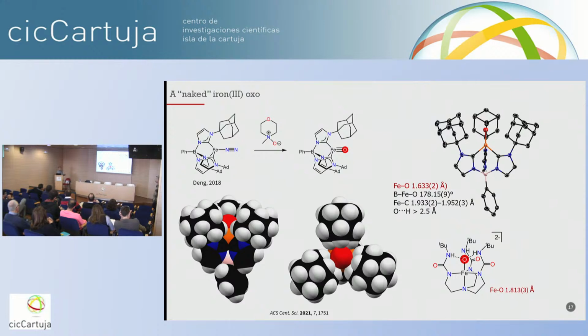Because it reacts with toluene when you heat it up. You synthesize it in THF, and I would be surprised if it doesn't insert the oxygen into the carbon next to the oxygen of the THF. The CH bond in THF is stronger than that in toluene. So it doesn't form a lactone or lactam or anything like that? Not that we can tell. I think this is pretty robust. If you heat this up in benzene, you can heat it to like 100 degrees, no problem for a few hours. You see a lot of papers with iron oxides and the like where they use substrates with benzylic CH bonds, and that's probably why they're easier to react. Okay.